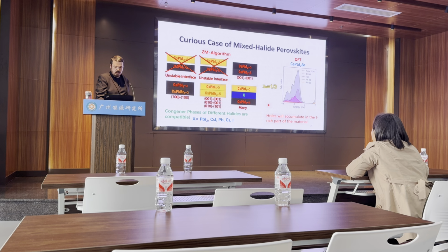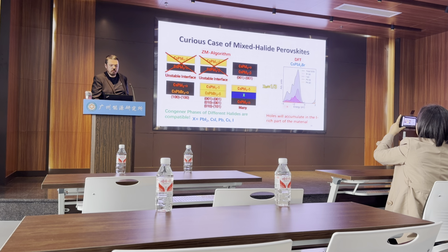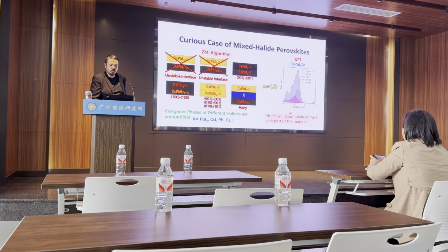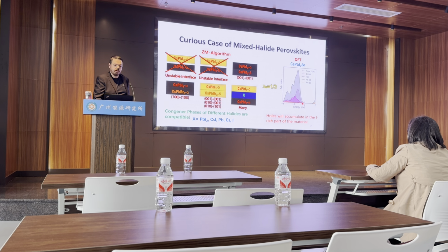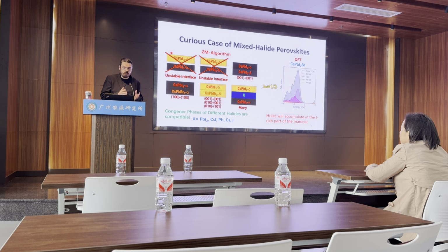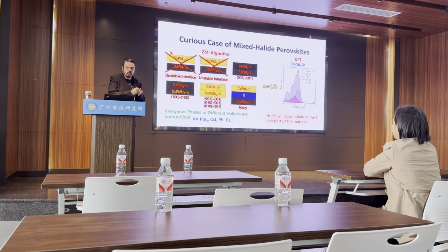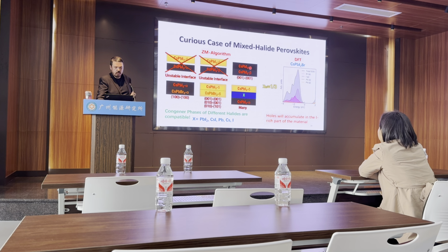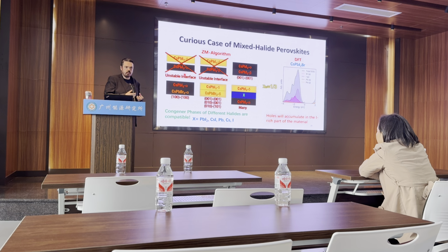Okay, this was a very early project a few years back. I was interested in mixed halide perovskites, so CsPb(I,Br)3. In this case, the big result, and also the big problem, is that holes will accumulate in the iodine-rich part, and that will cause segregation, and DFT confirms this. The other thing we wanted to know is which phases can actually combine together for real. What we found is black phases are all compatible, regardless of whether they're iodine-based or bromine-based. Yellow phases are all compatible, regardless. But yellow and black phases are never compatible. So the interfaces are always unstable.